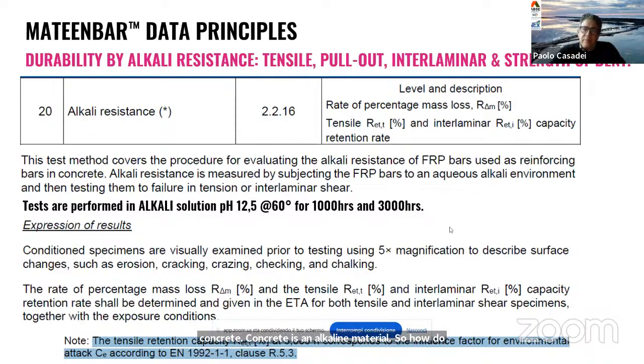Well, we simply test and we demonstrate that after 3,000 hours, there is a reduction in our property of less than a certain percent, and that is defined by the code. And that difference in this test allows us to aim at designing for greater than 100 years design life of our structure. So yes, there is a limit, but yes, there are ways to go around that, meaning to demonstrate that the producer is capable of outperforming this test, and so no limitation is given to the material.